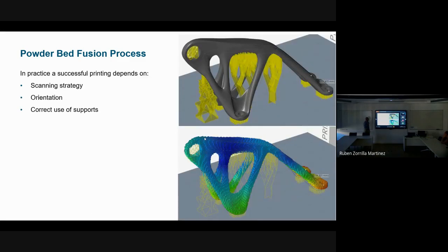So what are the important factors or parameters for doing SLM? Basically, if you want to create a correct piece without any defect, you should check your scanning strategy, which is important. It also depends a lot on the orientation. The entire deformation of the piece can change with the orientation of the piece, and with the correct use of supports. So supports have a very important role in manufacturing. In theory, you can create any shape, but in practice, you still have some limitations and some practical issues.